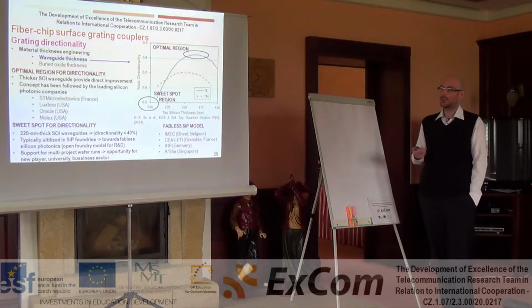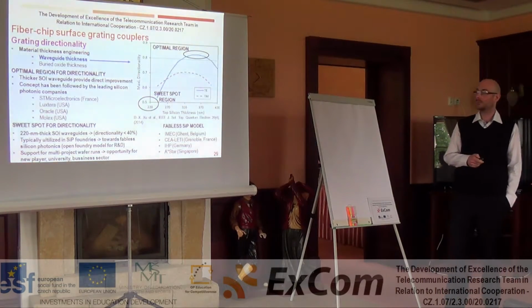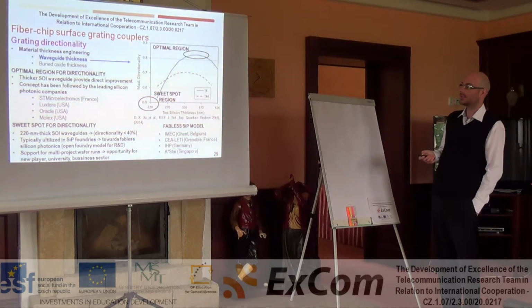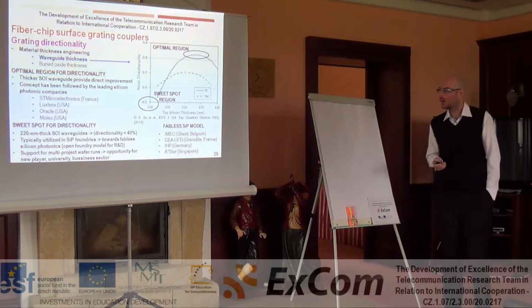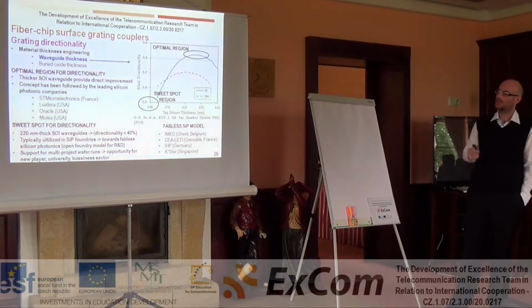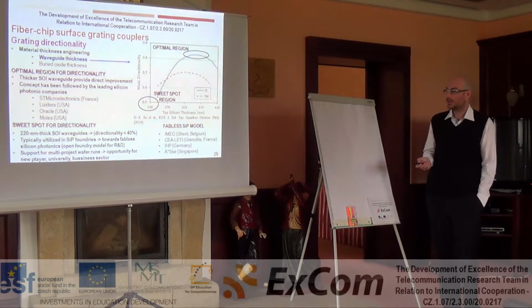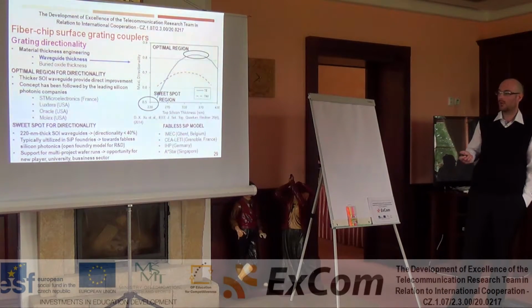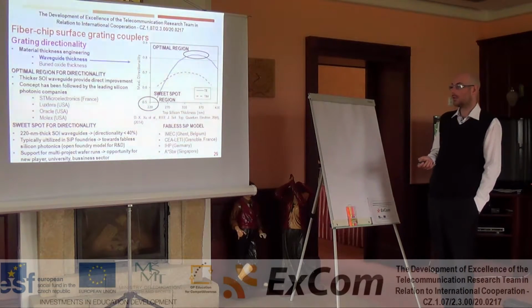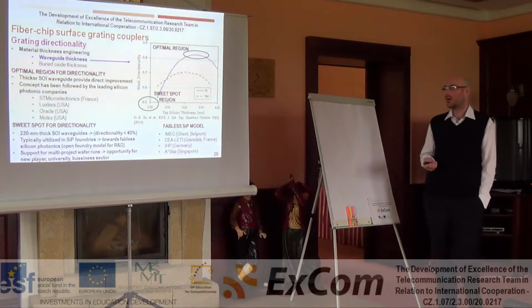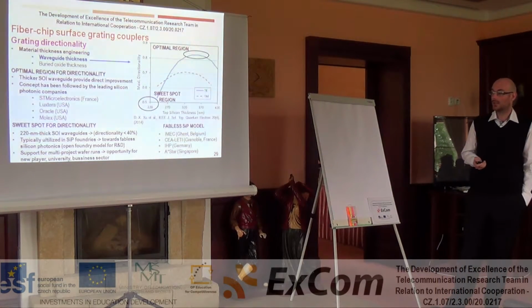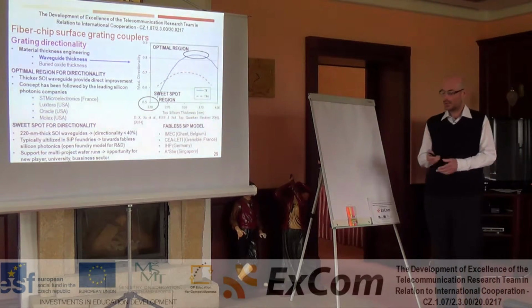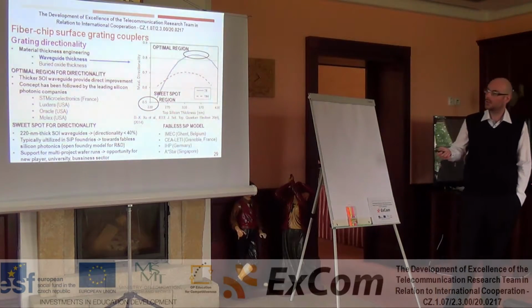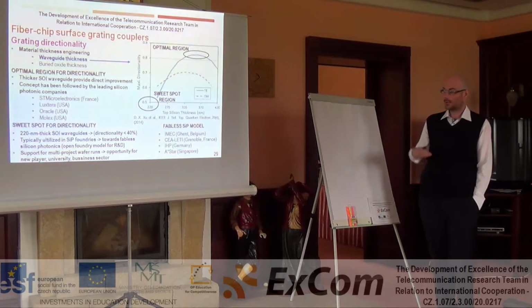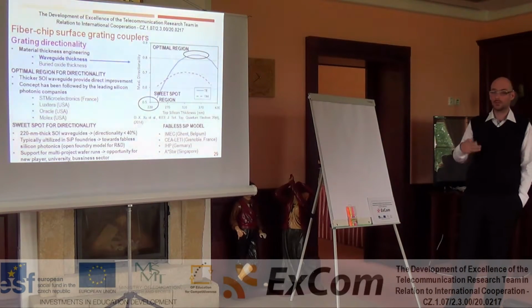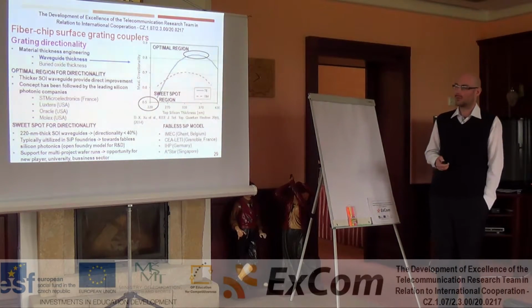However, on the other hand, especially in Europe and also in Singapore, silicon photonic foundries typically use SOI thickness of 220 nanometer waveguide thick silicon. In this way, the grating directionality is pretty low, below 40%. However, this kind of waveguide structures are typically utilized by silicon photonic foundries, which paves a way towards fabless silicon photonics. In addition, you buy your own place on the silicon chip, and this is a great opportunity for new players to design and develop your own devices.